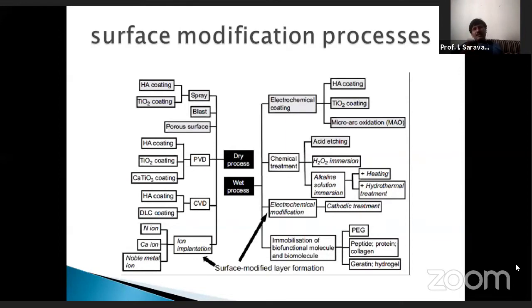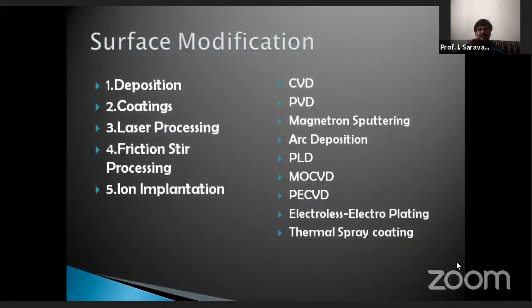What are the surface modification techniques? Coating deposition, spray coatings, laser processing, friction stir processing, and ion implantation are the surface modification techniques. The processes include chemical vapor deposition and physical vapor deposition. Under physical vapor deposition, magnetron sputtering is normally used for thin films, and cathodic arc deposition is used for hard nitride coatings, carbide coatings, oxide coatings, and dense coatings, and it is very good for adhesion. It is used for wear and frictional applications. Then pulsed laser deposition, metal organic chemical vapor deposition, plasma enhanced chemical vapor deposition, electroless coating, electroplating, and thermal spray coating. These are all the surface modification techniques and processes.